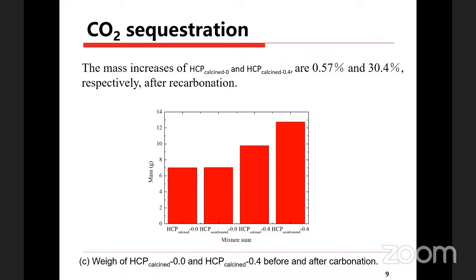That is another picture that we show about the mass increase. And we find that the role of water is quite important, the 0.4. If we add water, like a water ratio of 0.4, there's a great mass increase. That is 30% versus 0.5%. So this is quite different.